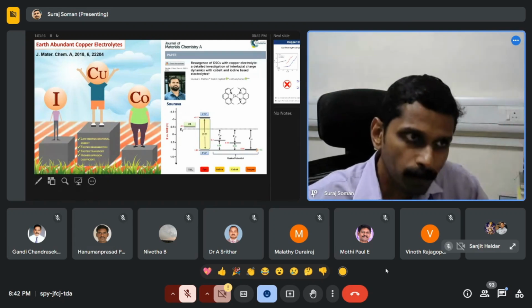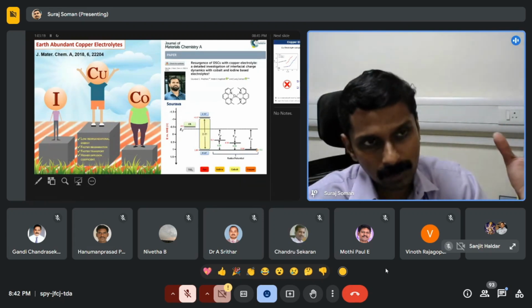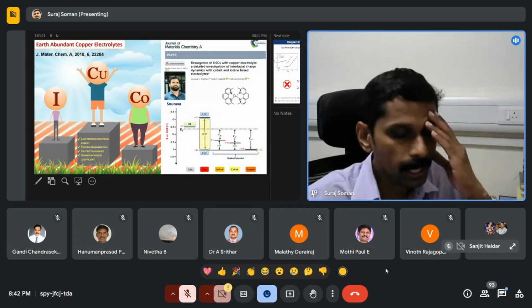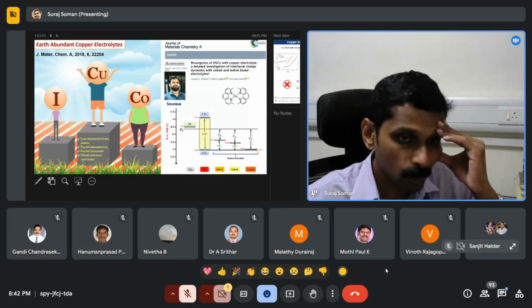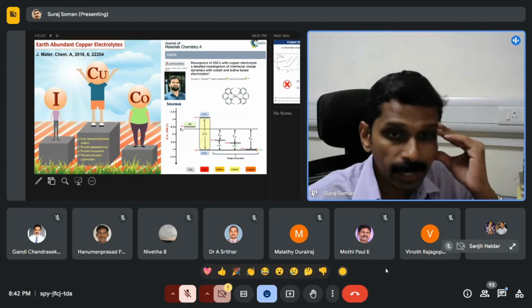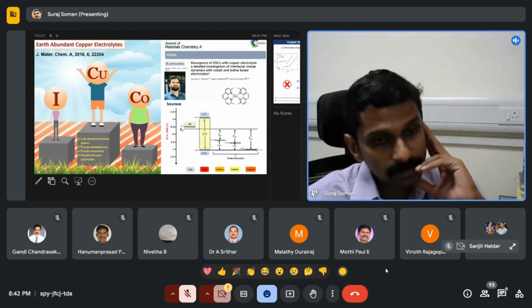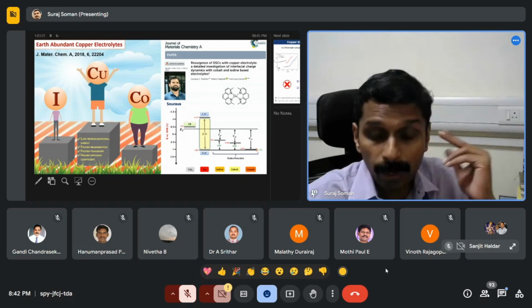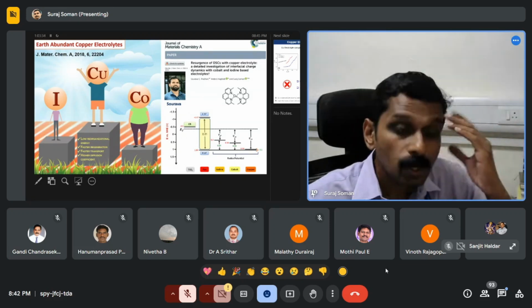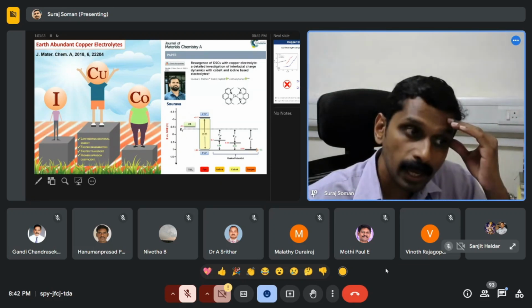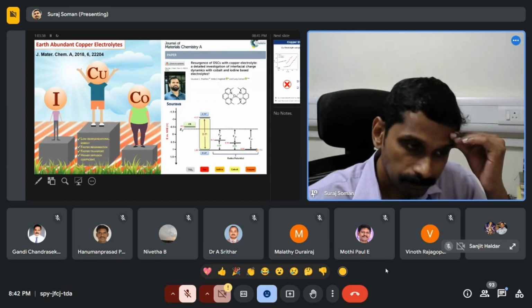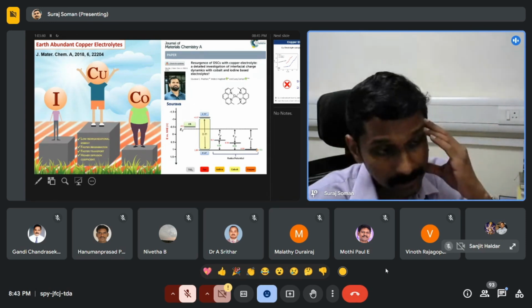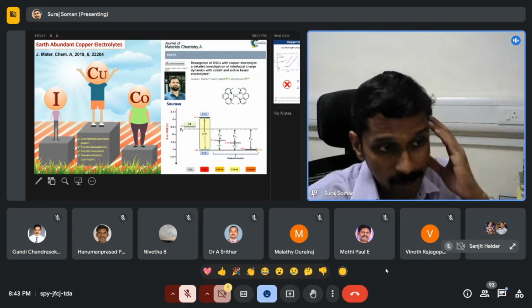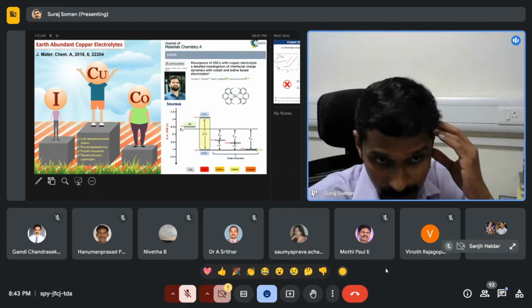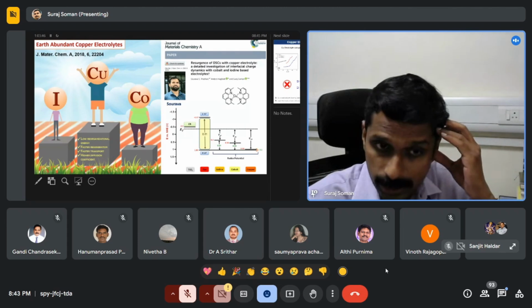So the copper-based system, this is actually one of the seminal works done in this area, where one of my students, Saurav, did a very systematic investigation on iodine, copper and cobalt. And what we found is that the copper system has a lower reorganizational energy. It has faster regeneration, better transport and higher diffusion coefficient. So here you can see the energetics.